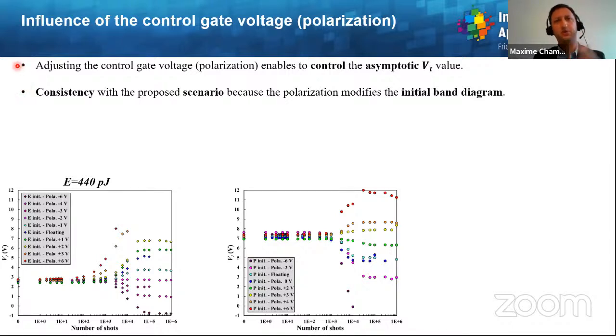The first experiment consists in using a control gate voltage, which is called polarization or bias. And here you can see the threshold voltage as a function of the number of shots for initially erased and programmed flash memories. One can see that by having different bias, you can play on the final state of your laser-induced programming, which means that adjusting the polarization enables us to control the asymptotic VT value.